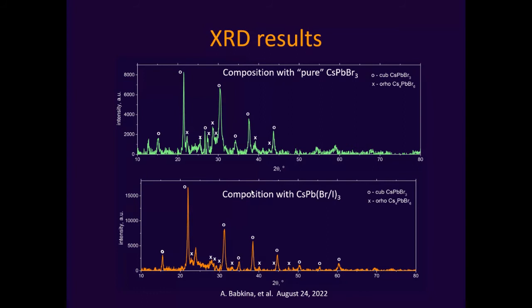But when we have a low concentration of crystals, it's a problem to measure XRD, because they're very small. Their quantity is very small, and they have dispersion in size, because it is a usual thing when you obtain nanocrystals inside of glass, also polymer. So if we try our best and make very concentrated glass with a very high concentration of nanocrystals, then in that case we can obtain such extraordinary results.